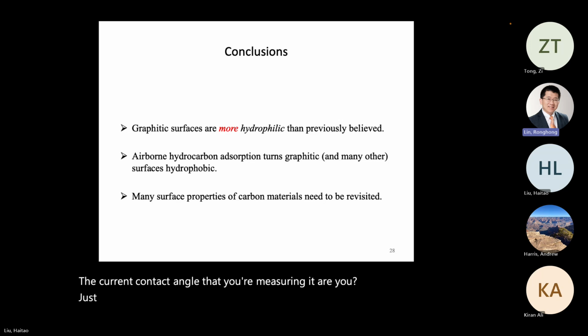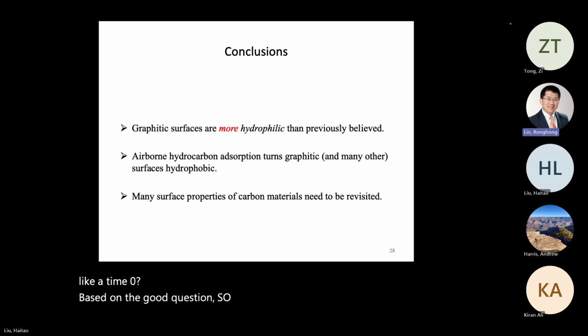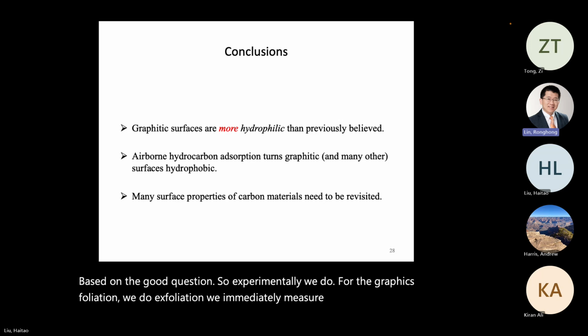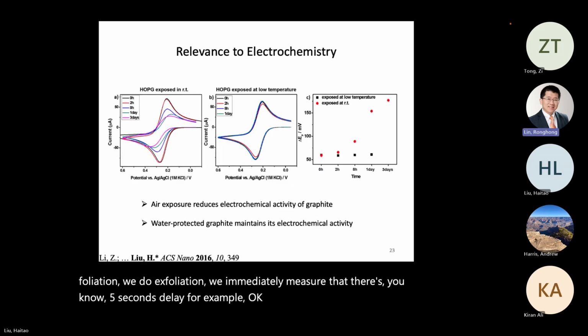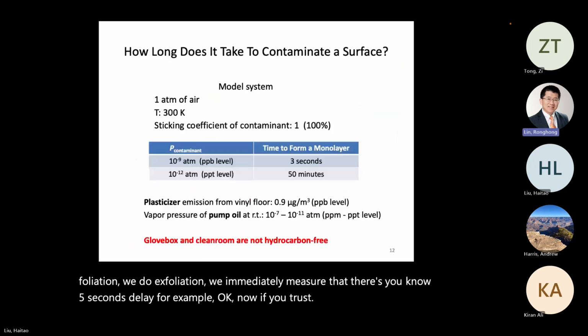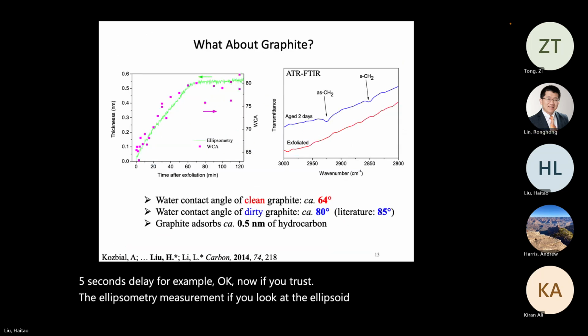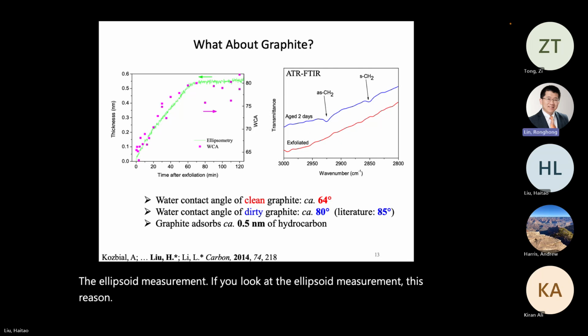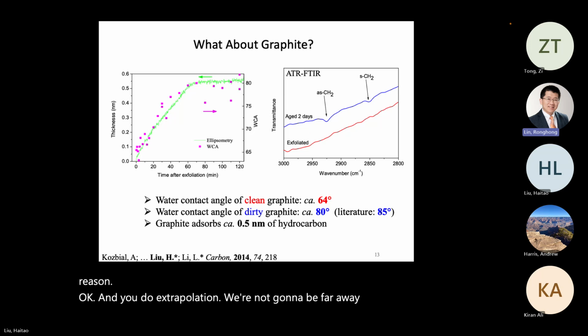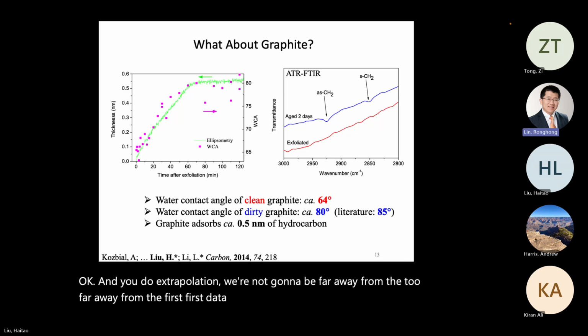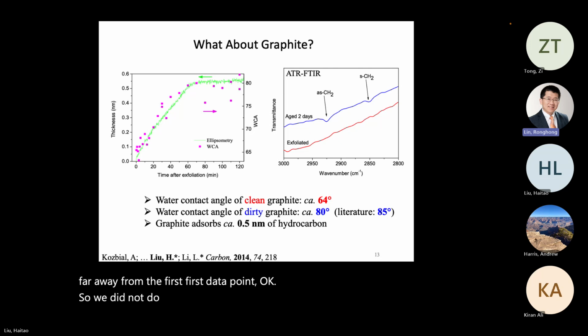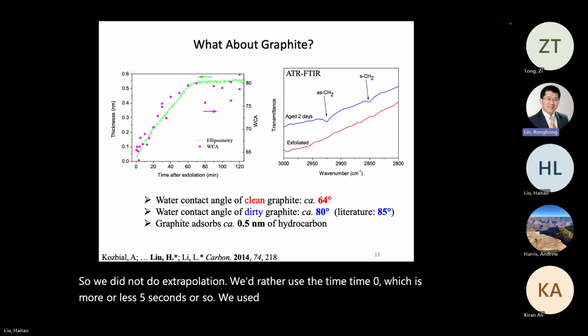Is it just at a certain time afterwards, or are you back calculating based on time to a time zero? Yeah, good question. So experimentally for the graphite exfoliation, we do exfoliation, we immediately measure with this 5 seconds delay, for example. Okay. Now, if you trust the ellipsometry measurement, it's reasonably linear. And if you do extrapolation, we're not going to be too far away from the first data point. So we did not do extrapolation. We'd rather use the time zero, which is more or less 5 seconds or so. We use that number.